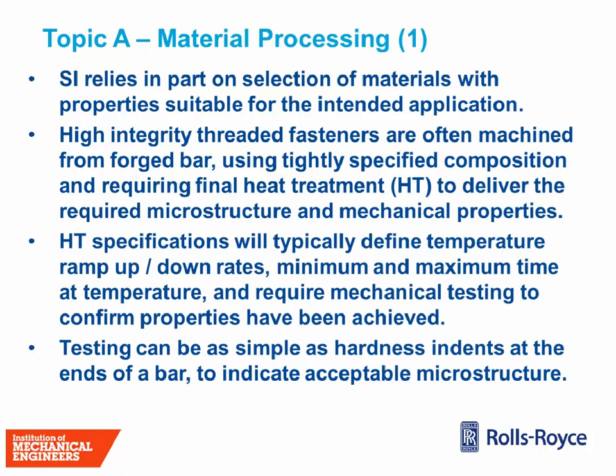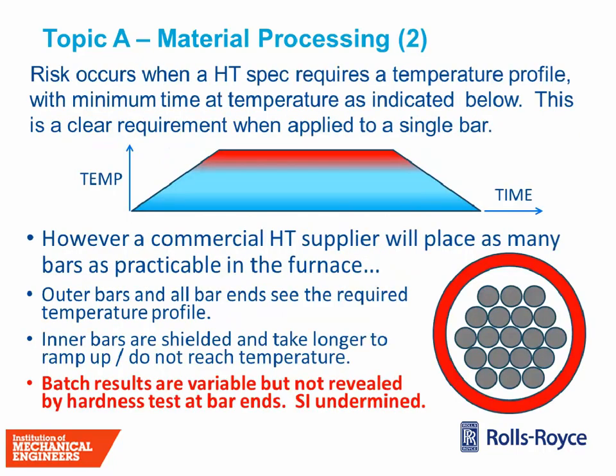Usually that means we've got to be quite careful about how we control the ramp up and ramp down of temperature in a furnace, and how long we maintain the heat treatment temperature. And then at the end of a heat treatment, we'll want to confirm properties. So we might go off and do quite detailed mechanical testing for a large forging, but for something like bar stock, where we're producing large quantities, typically we'll do quick and easy tests, such as hardness indents at the ends of a bar. And a hardness indent can be a good indication that the microstructure is acceptable.